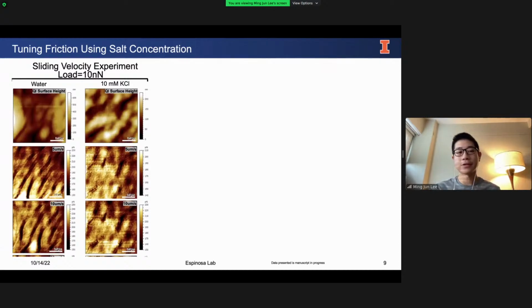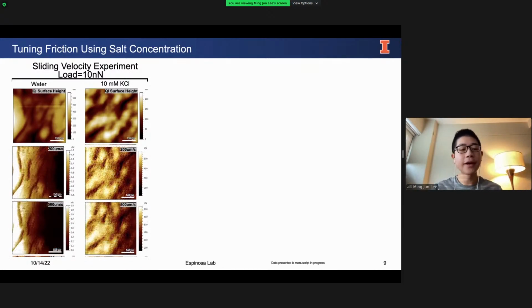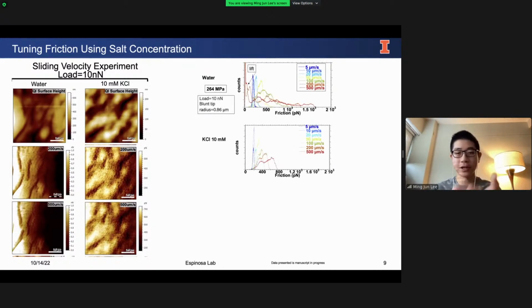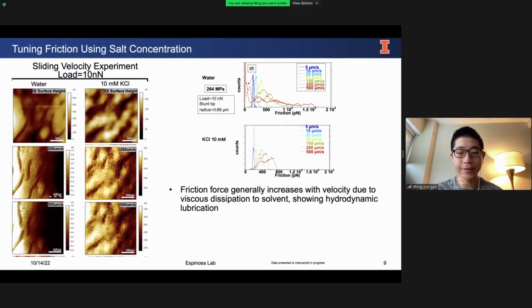Next experiment I'd like to show, I've reversed the parameters this time into the sliding velocity experiment. So now I fixed the applied load to 10 nanonewtons, but I changed the sliding velocity of the AFM tip, starting as slow as 5 microns per second, increasing to 10 microns per second. There are some intermediate speeds, and then finally ending off with 200 microns and 500 microns per second. Once again, the same positioning of the histogram values I've summarized here. And what I'm seeing is that friction force generally increases with the velocity.